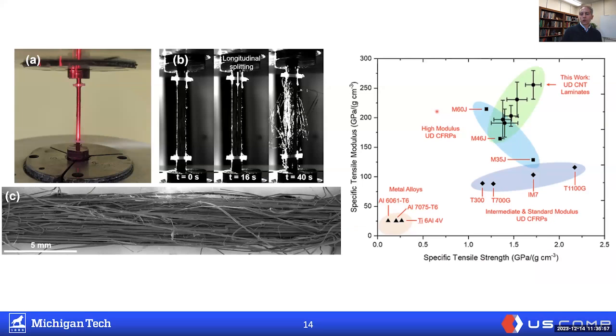So this material, and again, the citation was a couple slides ago, I encourage you to look at that paper if you want to see more details. But in that paper, we also outline the process of testing these laminates. This work was done at the University of Utah. You can see some of the images here. You can see that when they're tested, they do fail in tension. The yarns do break. It's not like they slipped out of the grips. They're very good at what they do there. They were able to get the failure to occur the right way. And you can see the failure mode.